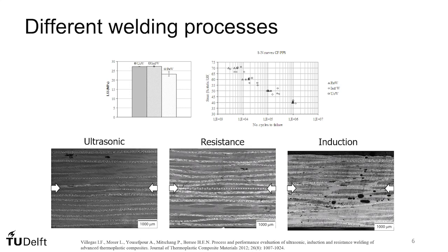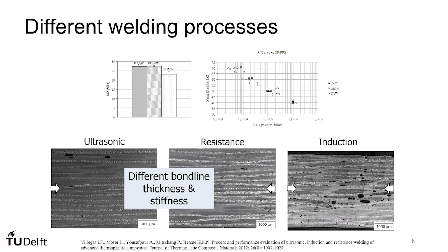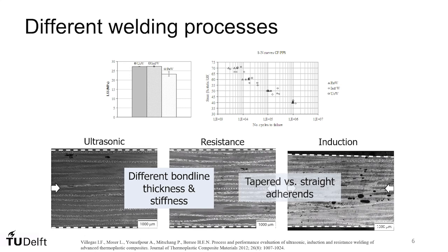line, which is indicated by the white arrows, was fundamentally different from the weld lines in induction and ultrasonic welding, in the sense that it contained an embedded resistive element, which is responsible for heat generation, in this case a metal mesh. Hence, the presence of the resistive element resulted in a different thickness and probably stiffness of the weld line in resistance welds. Secondly, the typical occurrence of through-the-thickness heating in induction welding, plus the application of the welding pressure, resulted in tapered adherends.